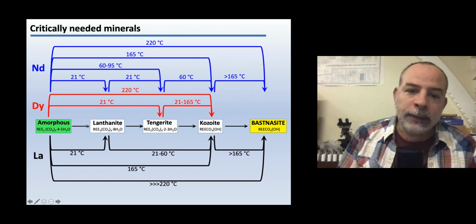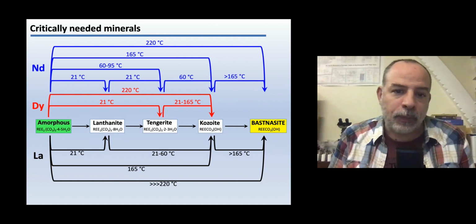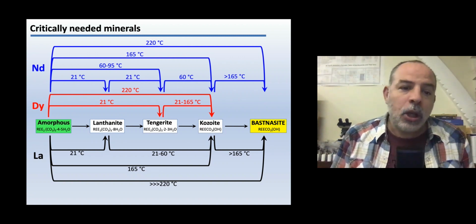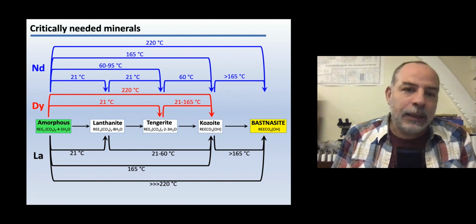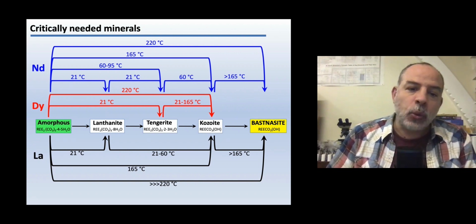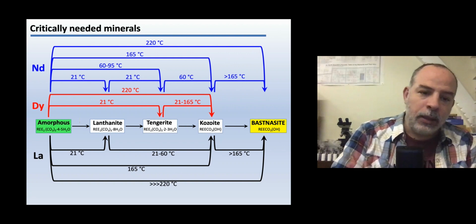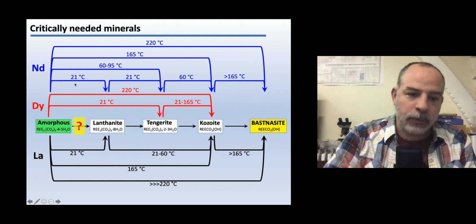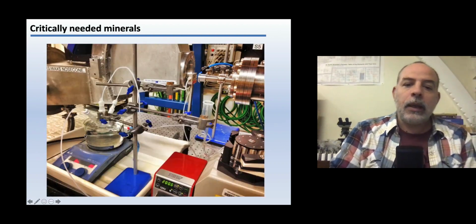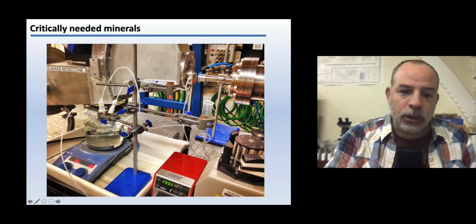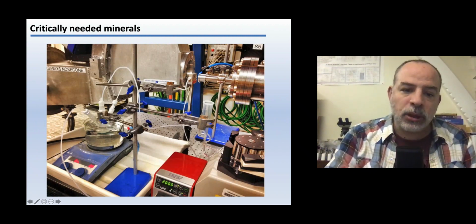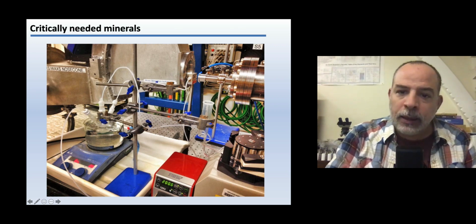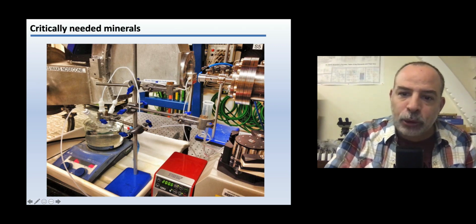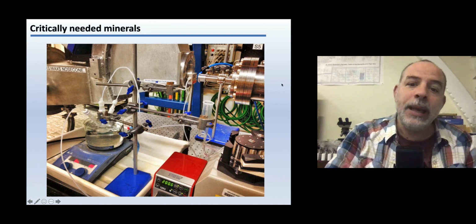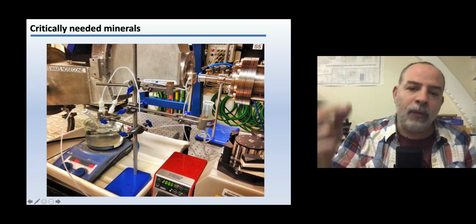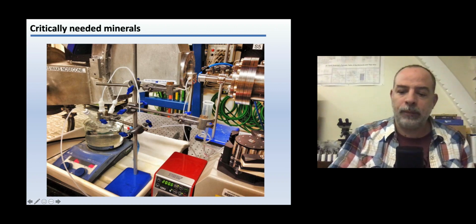So I'm going to show you one simple experiment using synchrotron-based diffraction, in which you're going to see the transformation from amorphous phase to this mineral named lanthanite, okay? Because we want to know what is happening here. All right. So what we do is we produce this lanthanite here by mixing solutions. Then the solution goes through this tubing and then through this capillary here, and the X-rays, the synchrotron X-rays, are probing the volume of water plus particles in there. So what do we see?